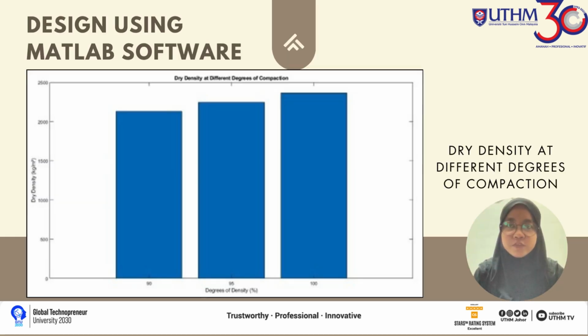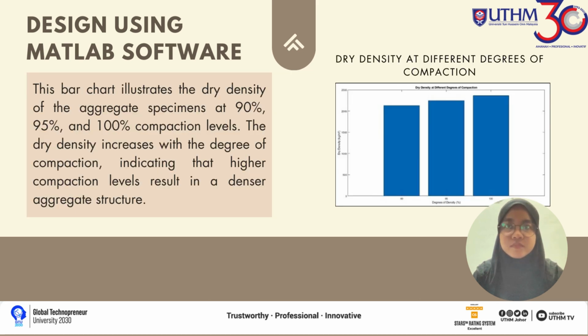So I will continue with the design using MATLAB software. First, dry density at different degrees of compaction. This bar chart illustrates the dry density of the aggregate specimens at 90, 95 and 100% compaction levels. The dry density increases with the degree of compaction, indicating that a higher compaction level results in a denser aggregate structure.